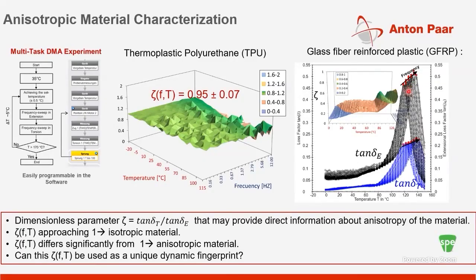They actually happen at the same temperatures, both in torsion and extension, but it's the relative intensities of this maxima which differ from the TPU case. This is due to the anisotropy present in the system, and you're probing different internal frictions, which is the interaction between your polymer, the matrix, and the glass fibers. The interaction actually differs depending on the kind of mode you're using as the deformation.